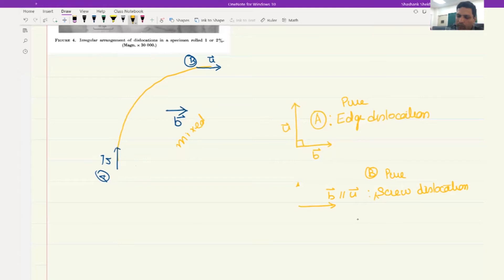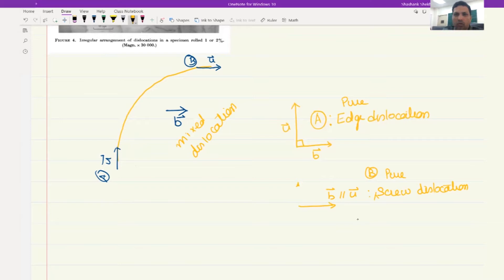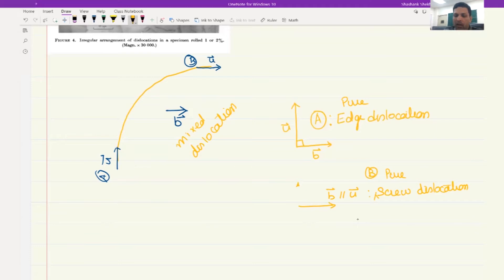In between these two points, what we have is called a mixed dislocation. So this real dislocation is actually a combination of edge and screw dislocation — it has partly edge characteristics and partly screw characteristics. Only where the Burgers vector is perpendicular to the line vector is it a pure edge dislocation, and where it is parallel it is a pure screw dislocation. Otherwise, a real dislocation would mostly be composed of what we call mixed dislocation.